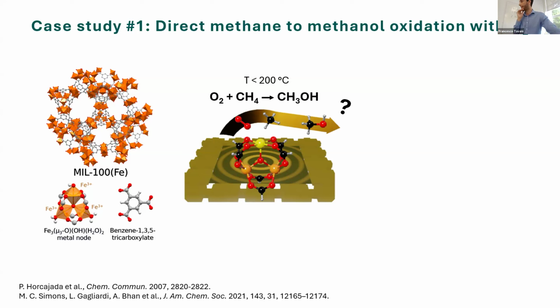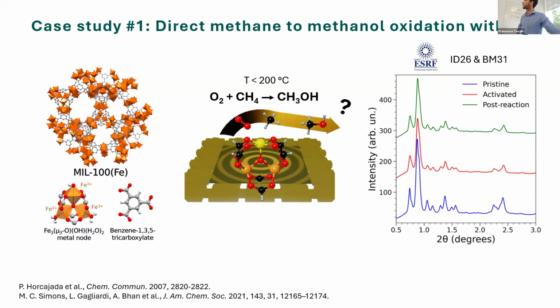There had been previous work by the Gagliardi group and collaborators investigating this system and this reaction in the presence of N2O, a different oxidant, more expensive and less abundant, and we were curious to see whether this reaction could also occur in the presence of oxygen. So we performed all these complementary synchrotron measurements at the European Synchrotron facility in France. And here I am displaying the X-ray diffraction patterns of the pristine MOF, thermally activated at around 200 degrees for a certain amount of time to remove the physisorbed molecules, and the XRD pattern of the MOF after the reaction.